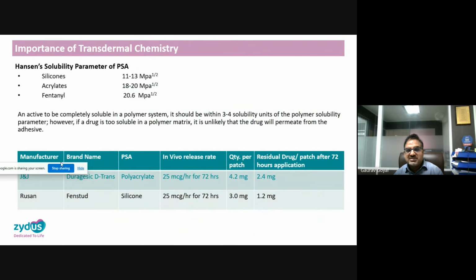So one very good example. This is one of the examples from my PhD research work, where I want to show how transdermal chemistry plays a very important role in the manufacturing of transdermal systems. So generally, these polymer adhesives, which are known as PSA, pressure sensitive adhesives, have Hansen solubility parameters from the literature. So silicones have a Hansen solubility parameter of around 11 to 13 megapascal, 18 to 20 for acrylates,